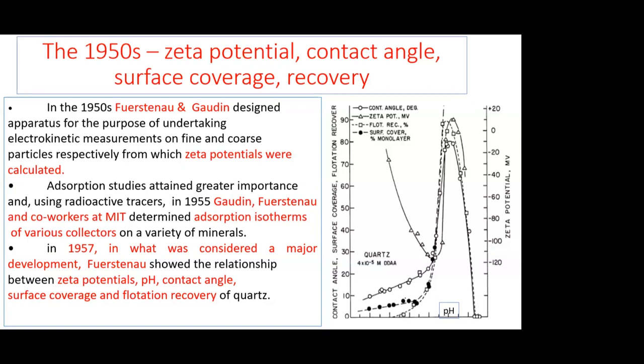I want to make a comment about surface coverage as a parameter. I think often we see results presented as dosage, but a much more insightful way to present collector addition is the surface coverage. And so we see that the zeta potential switch happened at a point where the surface coverage was approaching a total monolayer. And at the same time, you can see there's a very high sudden increase in the flotation recovery and in the contact angle.